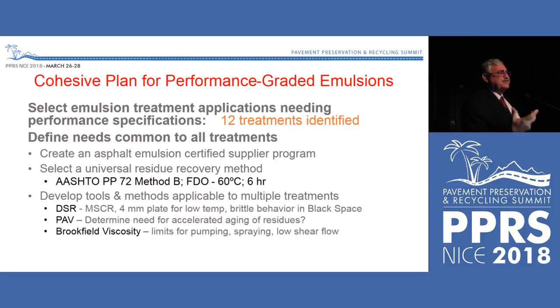So all the tests we currently use don't work anymore because we don't have enough residue, and we don't want to heat and pour the residue. We want to test the residue as it cures. That's at 60 degrees C or less. So now we have to totally rethink everything we're doing to test residues and specify residues in the context of the recovery method that gives us a limited material, and we never want to heat over 60 C. So we are developing test tools to do that.